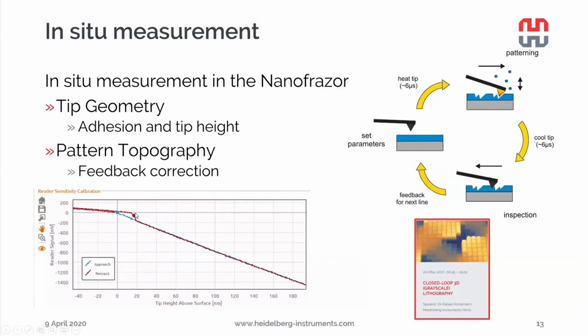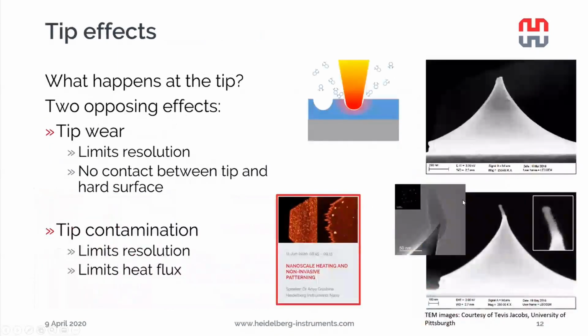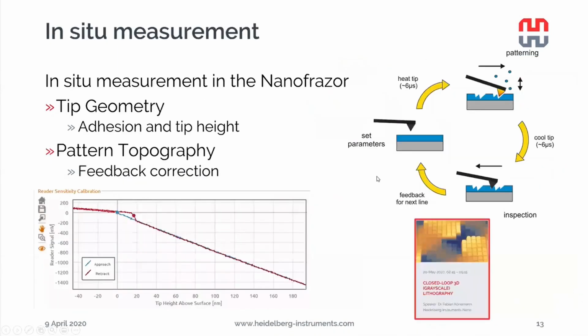And this tells us a lot about the adhesion length. Basically this triangle. And the larger this gets, this tells us we have a larger tip adhesion to the surface, and this usually corresponds to the tip diameter. So if this triangle here gets larger and larger, we see that we have a larger tip diameter. We can also get basically the tip height, this distance, from this approach curve, and therefore have two nice parameters that tell us a lot about the tip state already. The second part is small changes at the tip when there is something smaller than this growing also change the patterning performance a little bit.